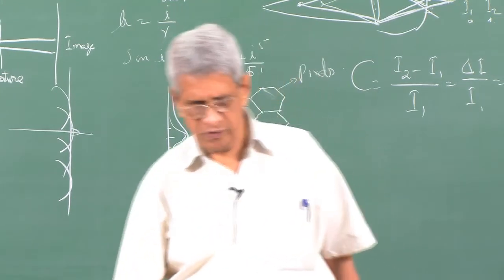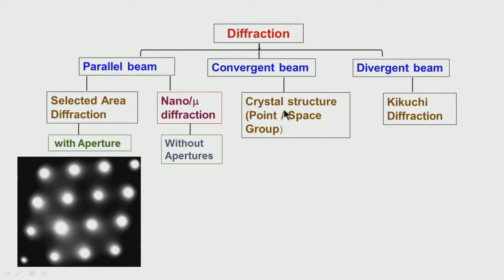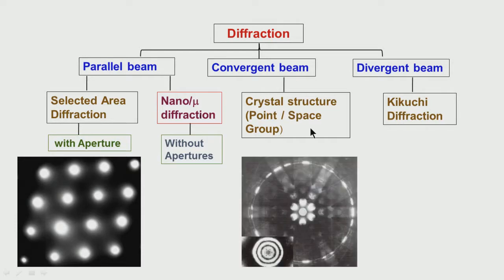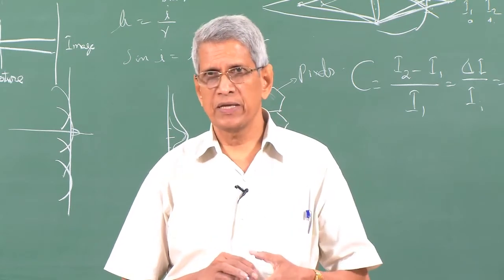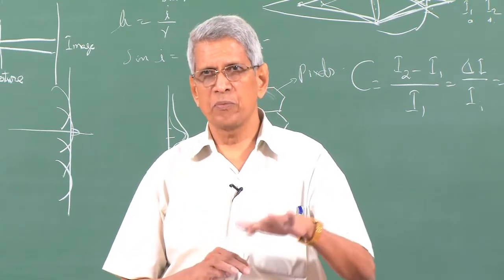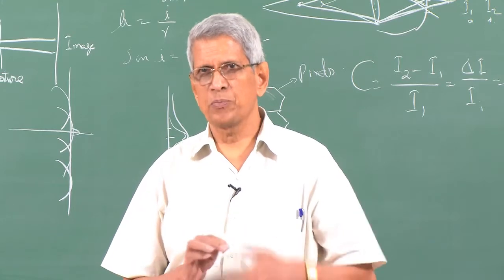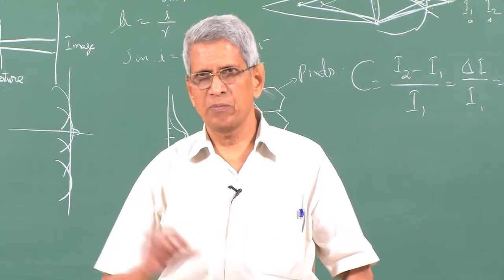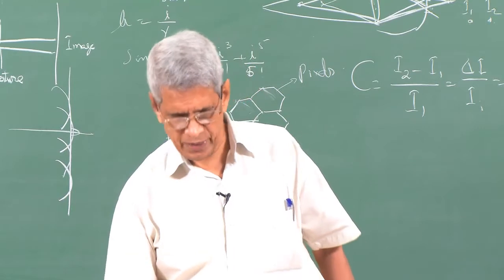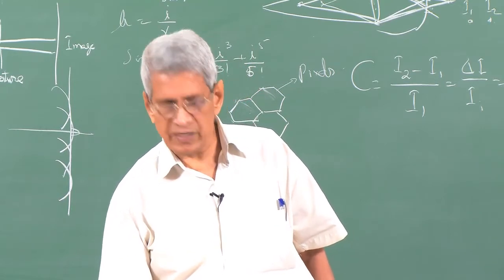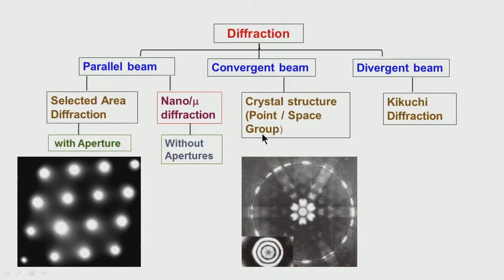This sort of diffraction gives rise to a pattern like this, where not only the zeroth order zone, higher order Laue zones also we can get simultaneously. This way, almost the full reciprocal lattice, the various reciprocal lattice sections, we can get information about how the diffraction is occurring. From this we can get the crystal structure, point group, space group determination, all these things could be done. This will be talked about in a separate lecture later.